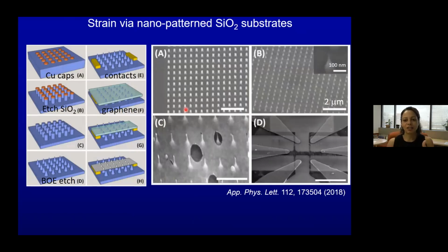And so this one I started with a graduate student. So after a couple of years of working on it, the project finally graduated to a graduate student working with an undergraduate and making lithographically defined features. So here we want to make something for transport. So we ended up making something on silicon oxide substrates, which is the standard device material. And what we did is we started with a silicon oxide substrate. So imagine this blue part here is just silicon oxide with doped silicon underneath. And we put on copper caps that were of the scale of 100 nanometers, about 100 or 200 nanometers.